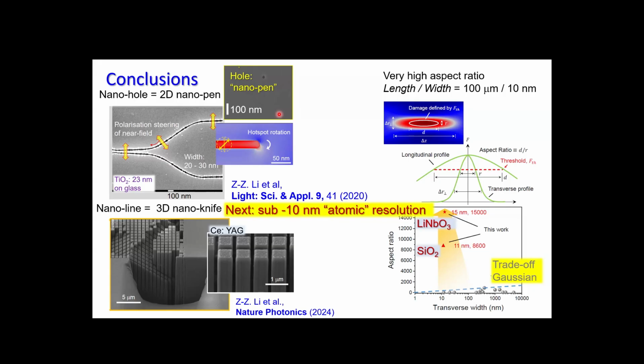Yeah, we want to modify inside the volume. So we want transparency inside the volume, but then there is no way we can deliver energy for the required modification. If you have glass or sapphire and you are focusing your laser, and you are not reaching the required intensity, light just gets through, energy is not delivered, no modification, and you can't benefit from this. So we need to drive material modification in a very controlled way. Dielectric breakdown is something less controlled, but just in these epsilon-near-zero conditions, when we have a material where we can deliver energy, as you see, it can be on nanoscale and very well localized, and because of that the modification is really nanoscale. This is how we can write and modify material. So transparent material needs to become not transparent, but in the places we want.